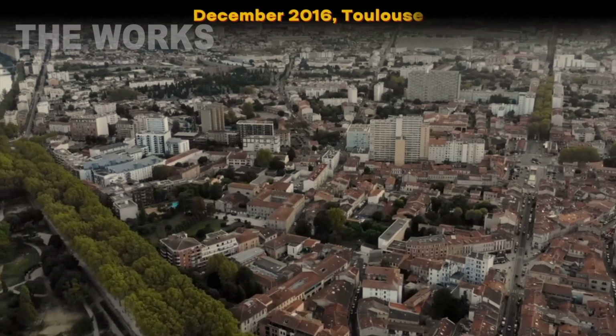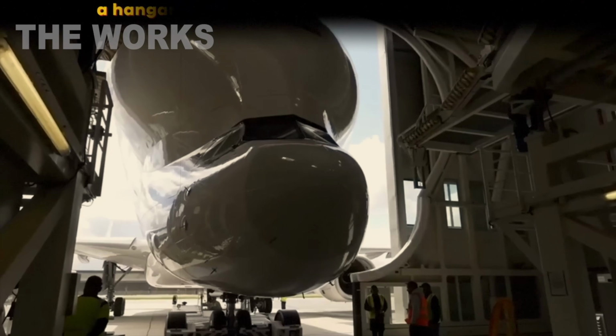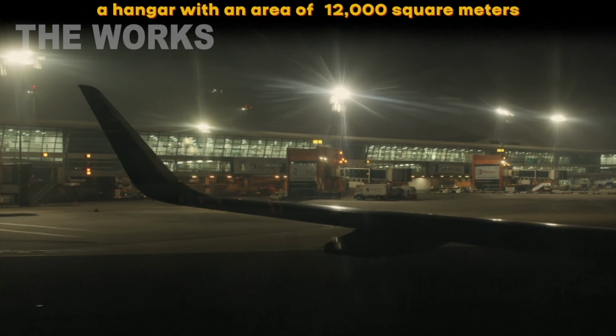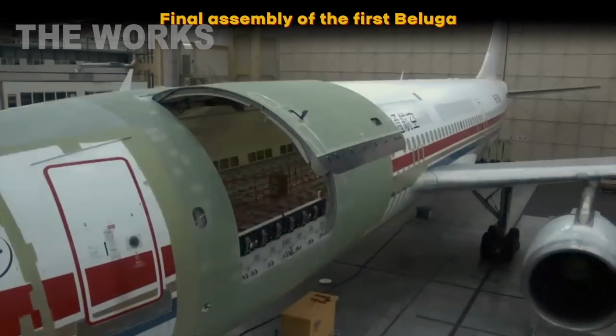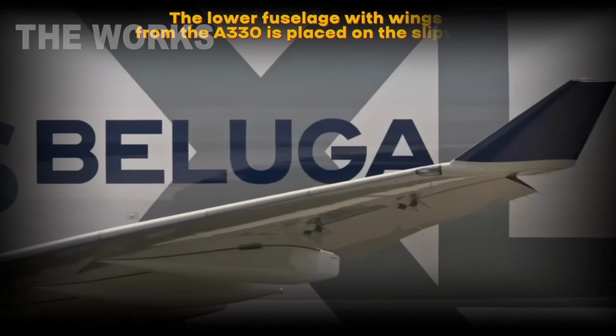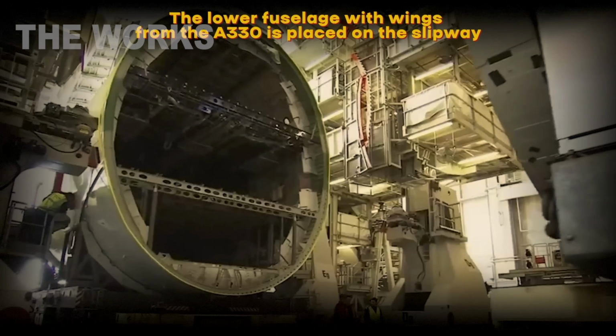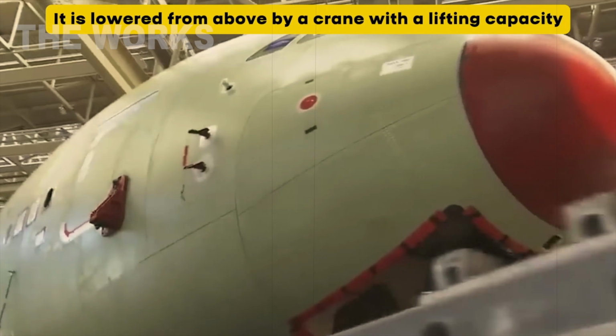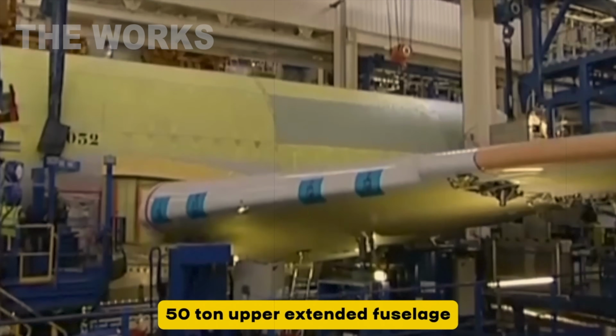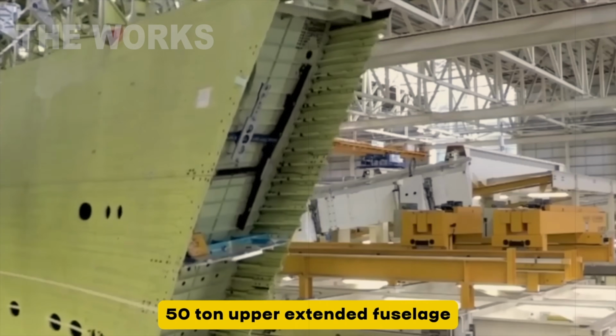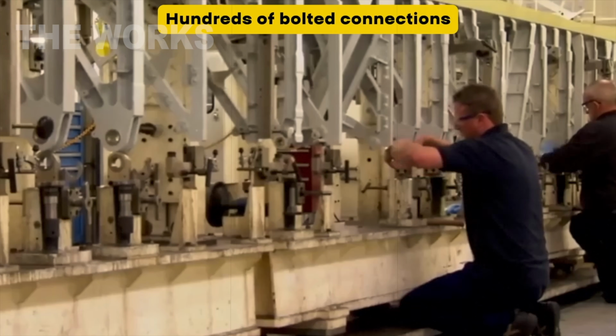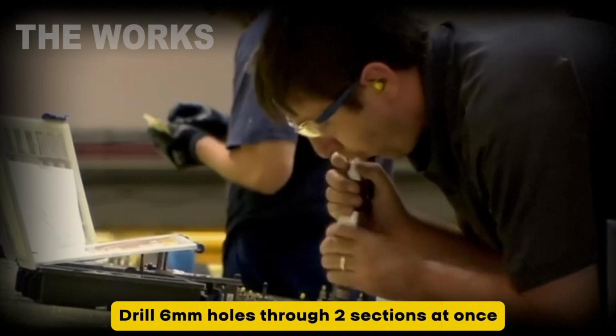December 2016, Toulouse. Line L34, a hangar spanning 130,000 square feet. Final assembly of the first Beluga. Lower fuselage with wings from an A330 goes on the jig. From above, a 50-ton crane lowers the expanded upper fuselage. They mate the perimeter. Hundreds of bolted connections. They drill quarter-inch holes through both sections at once, tolerance plus or minus 0.04 of an inch.